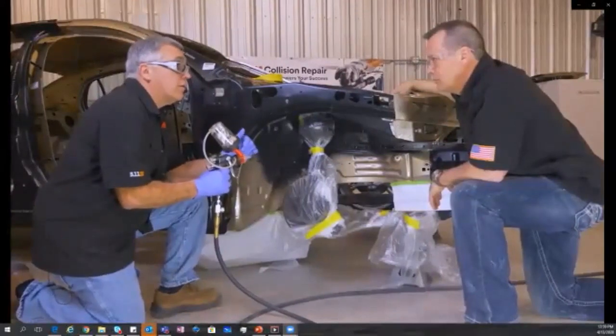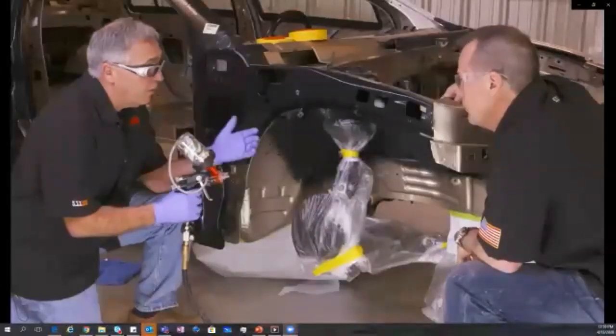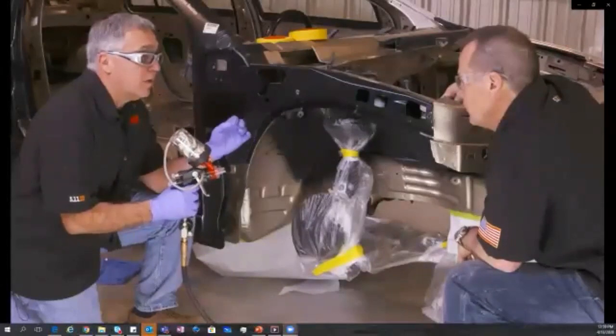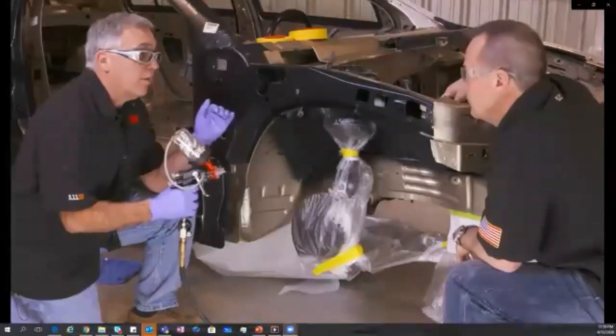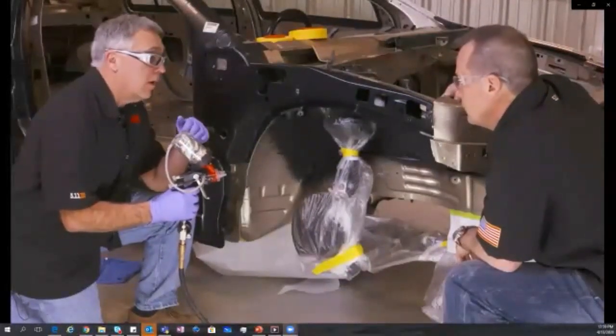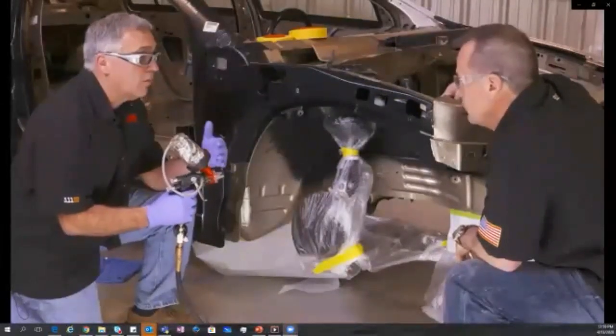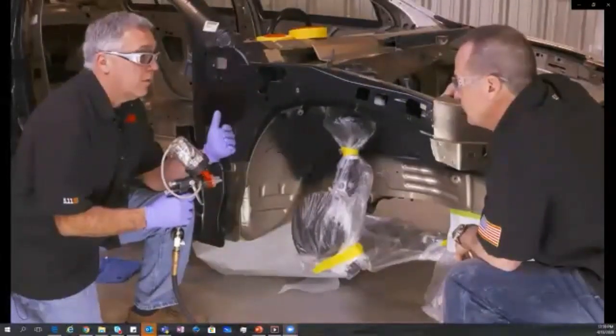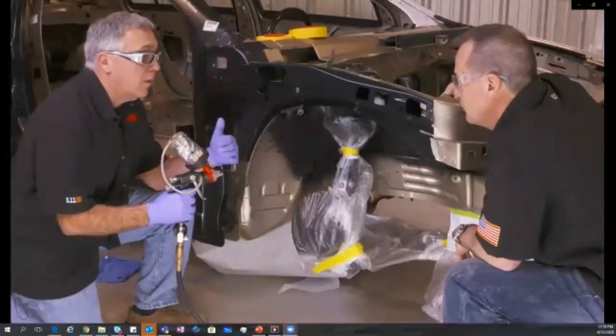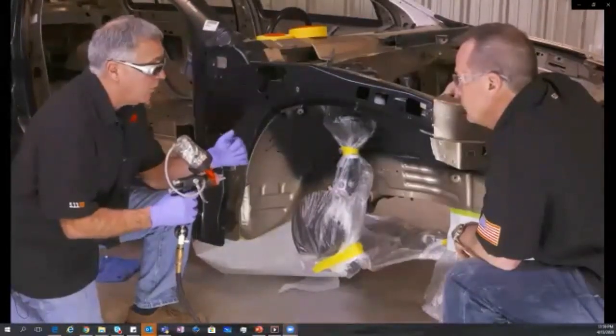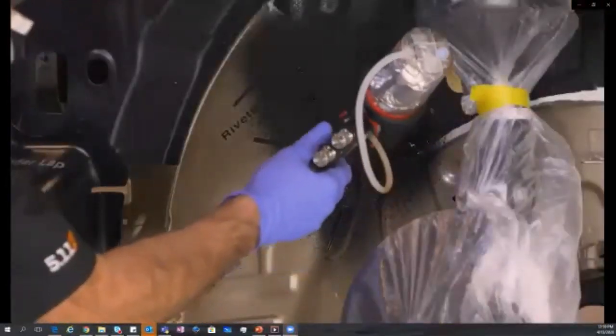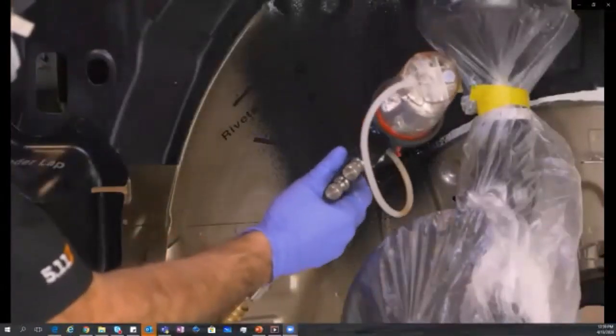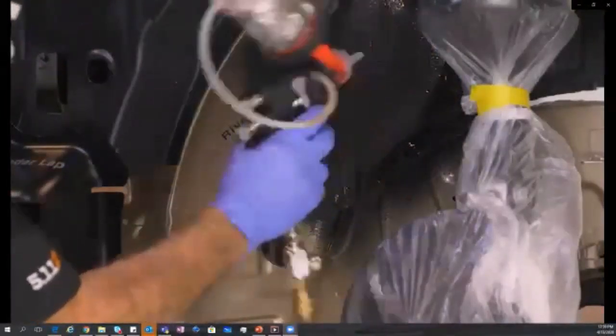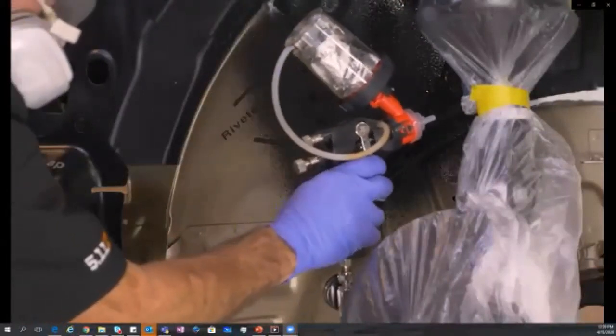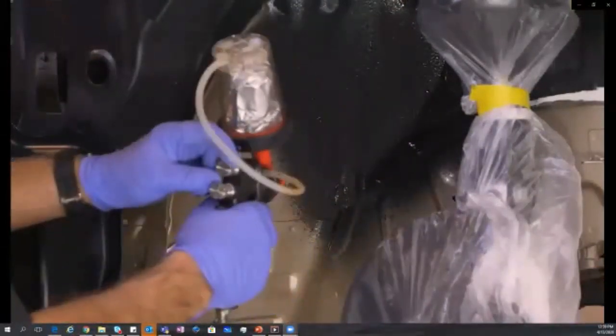And so this type of material, believe it or not, has about a 50% shrink rate from a wet mil thickness to a dry mil thickness. And I've seen that across many different products related to undercoating. So it's not just this particular one, but in general, that's a rule of thumb. And so we found if you put four coats on, it's going to give you 20 plus mils. Now it depends on the settings on the gun, sure. Right? So I had some pretty heavy coats I applied on here.